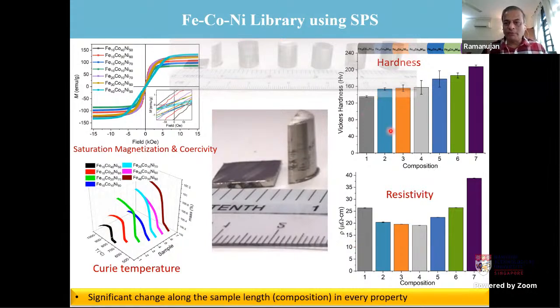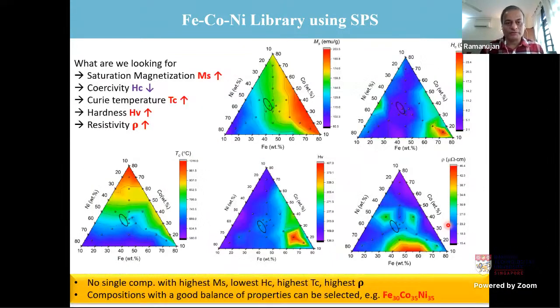And we measured the mechanical properties as a function of composition using nano indentation, which is very fast, and electrical resistivity. So you can see that we've created a materials library in which we have a bunch of different compositions in the ternary space, and we've measured various properties. So here are our results. You can see that we can plot the saturation magnetization, the coercivity, the Curie temperature, the Vickers hardness, and the resistivity. Typically for AC magnetic applications, you will prefer, for example, high electrical resistivity.